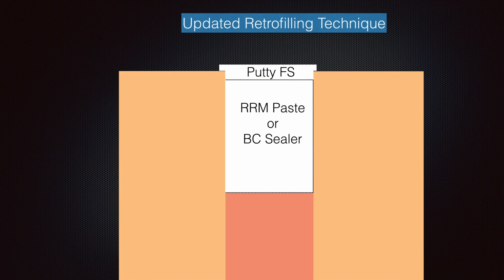Because they're both the same base chemistry, they will interact and they will basically fuse to each other. But because the putty material has some components that increase its washout resistance, and the putty is fast set, it sets in about anywhere from 5 to 20 minutes, whereas the syringeable material could take 4 hours to set. What ends up happening, if you fill the whole thing up with the syringeable material and then you close your retrofilling, the blood will come in and basically wash out the material because it hasn't set yet. But if you use the putty as a cap up on top of it, the putty will act as protection for the material to set.